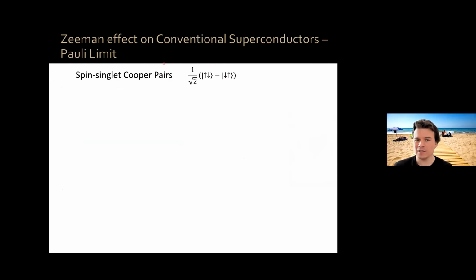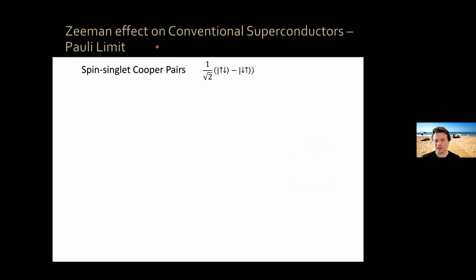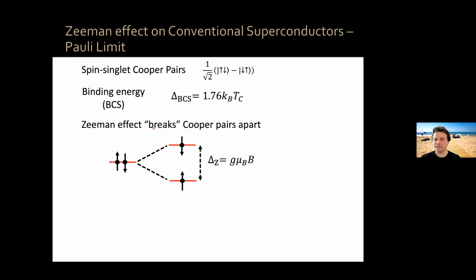Now, usually, in conventional superconductors, okay, your Cooper pairs have a spin singlet configuration, right? And the binding energy in BCS theory is given by your superconducting gap, which is 1.76 times k_B T_C, okay? Now, if you apply a Zeeman magnetic field, the Zeeman effect breaks apart Cooper pairs, because you have spin up and spin down electrons. The Zeeman splitting is equal to g mu_B B, okay?